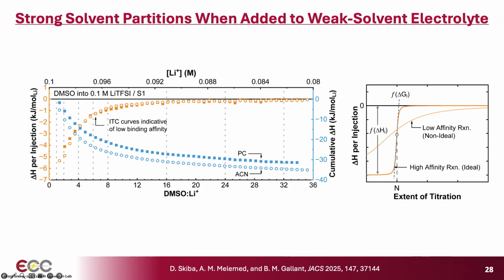So this graph now shows the ITC result for such an experiment using propylene carbonate or acetonitrile as the weak solvent, DMSO as the strong solvent, and 0.1 molar lithium TFSI as the salt. And so the response, delta H per injection, is shown here in orange. And you can see right away that we do see a displacement reaction occurring as DMSO displaces these coordinating species in the environment of lithium. However, it is a low affinity reaction, so we don't see the nice sigmoidal response that we would need to be able to directly pull out the thermodynamics.